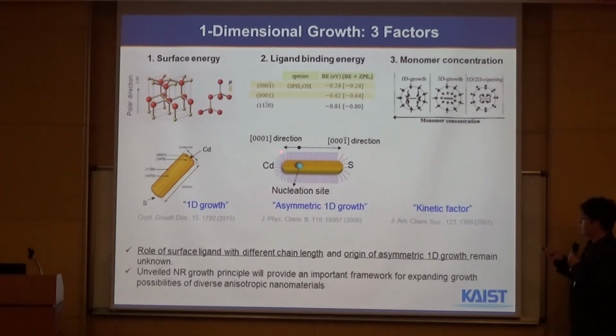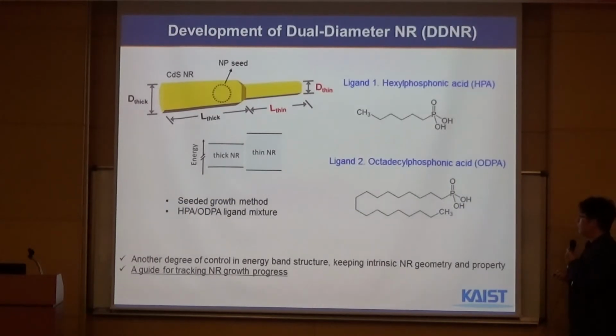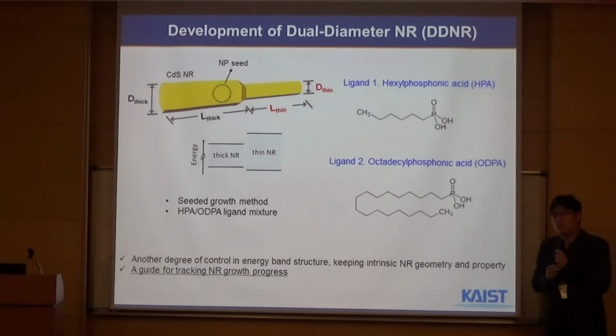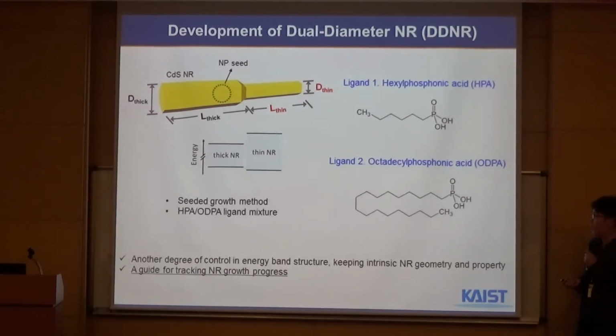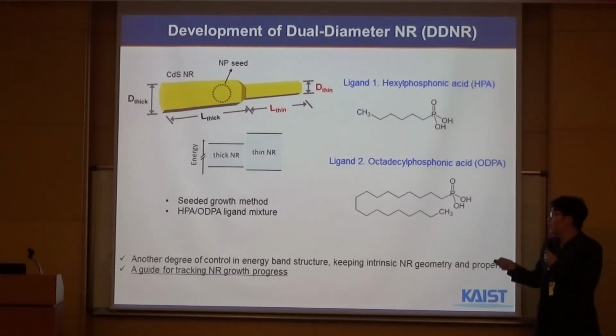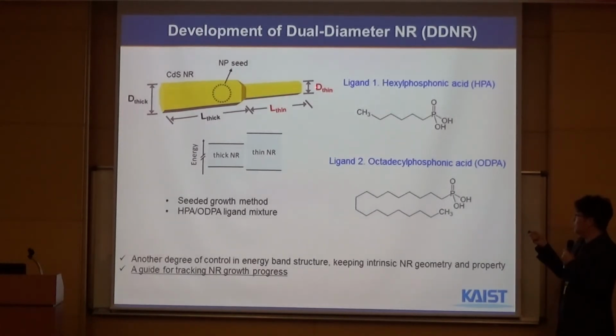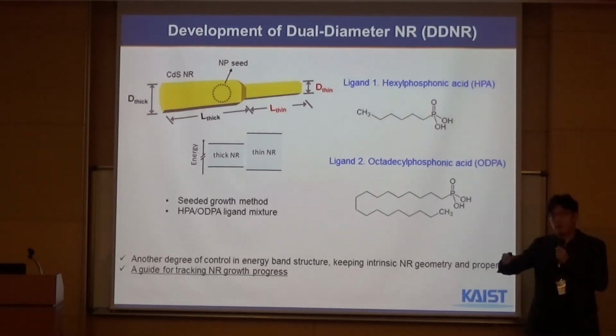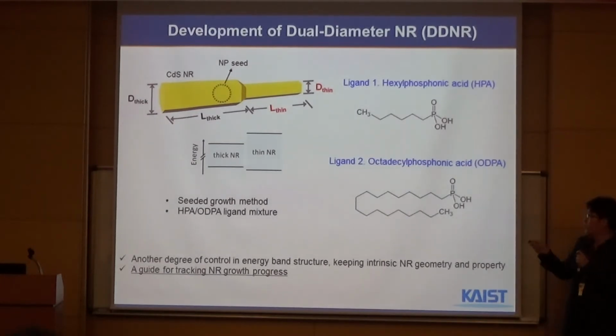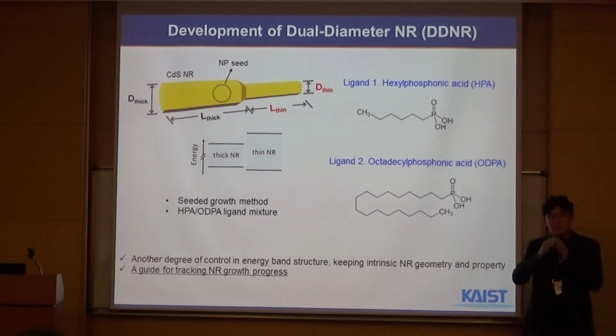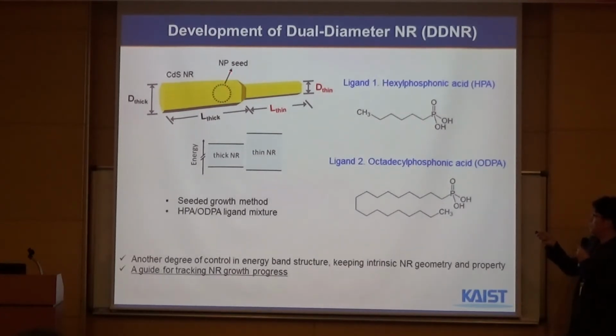By modulating the ligand on the surface, we were able to make dual diameter nanorods for the first time. And the beauty of this structure is that we can actually study the growth of this direction versus this in very long time. It's very difficult to see when you have single diameter nanorods, because it's going to look the same regardless. But if you have these dual diameter nanorods, now you start seeing the growth direction in this way and that way, and you can monitor the growth patterns over time.